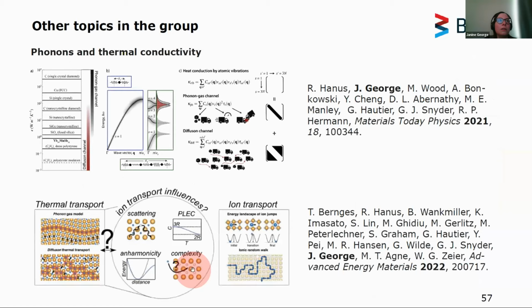Now, I also wanted to mention that we're working on other topics, especially related to phonons. In recent years, we've contributed to papers where we looked, for example, at phonons and thermal conductivity in thermoelectric materials. We've used harmonic phonons and models for scattering to understand the thermal conductivity in very large crystal structures, such as 14-1-11, where we already have a transition from crystalline to glass-like materials, and where diffusive properties also play a role, with phonon band structures where bands lie really close together so that there are interactions between these kinds of phonons. And we've recently also had a look at this diffusive transport and its relationship to ionic transport in materials.